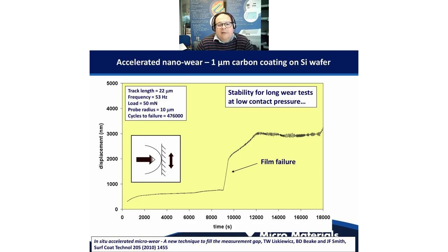This is what output data tends to look like from these tests. We don't just assess performance in terms of visual of the wear track itself. So here we're looking at a 1 micron carbon coating on a silicon wafer, and a test which is 18,000 seconds long, so it's a long duration test. We're oscillating at, I don't know why we chose exactly 53 hertz, and a 22 micron track length. So the sample is oscillating back and forth at 53 hertz with this probe applied with 50 millinewtons, 10 micron radius contact. And what we see is a change in displacement over our test duration.